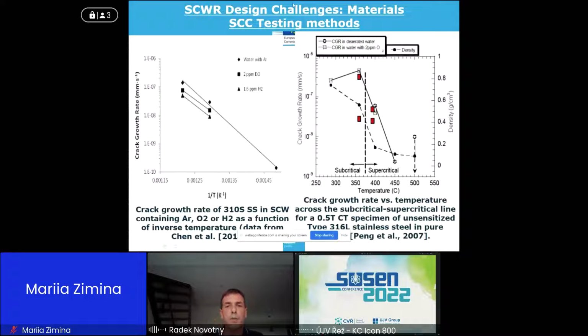And there we start measuring 1,000, 2,000 hours of real crack growth due to corrosion, stress corrosion cracking. We are using an online monitoring system to get the crack growth. We are using the direct current potential drop technique, and we are measuring crack growth in situ depending on load.